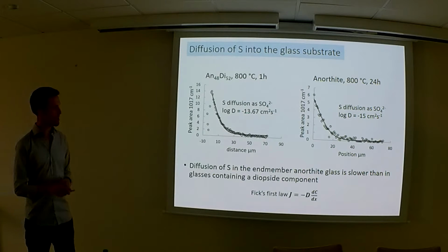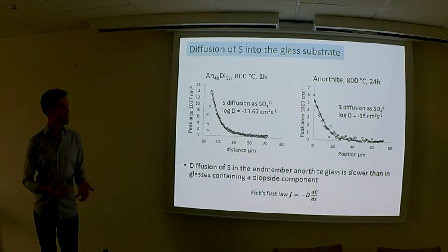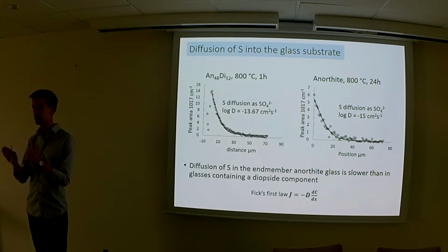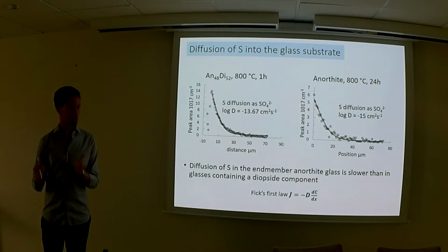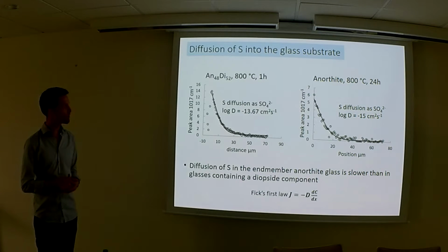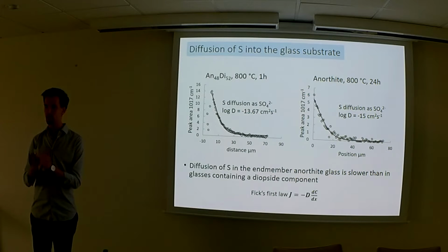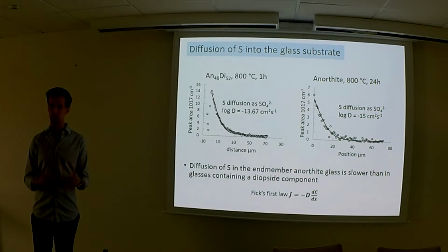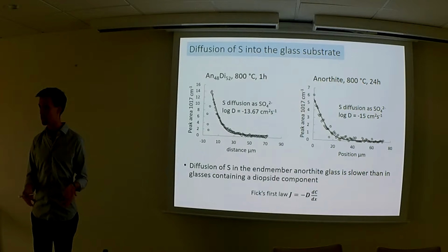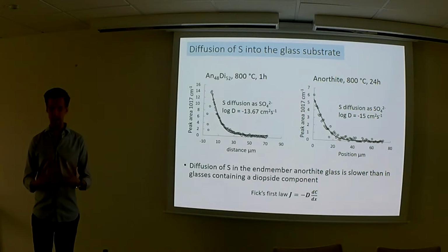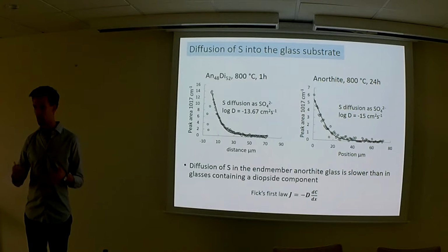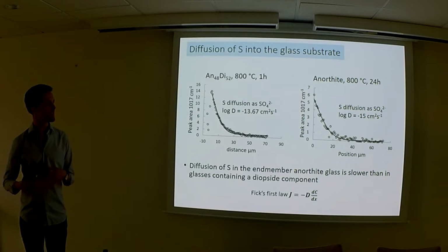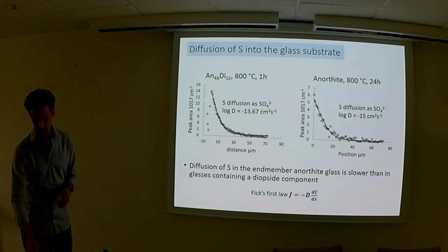It turns out from some estimates of how much calcium we lose and how thick these layers are where calcium is lost, that both calcium and sulfur diffuse during these reaction experiments at a higher rate than you would normally expect from classical diffusion studies. So somehow the reaction changes the driving force of the calcium and sulfur movement, increasing its rate of movement.